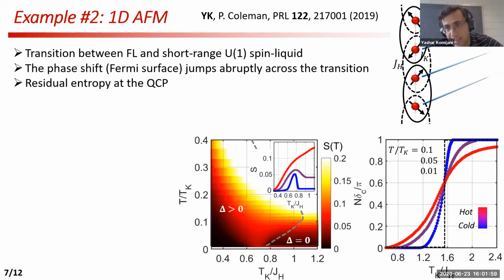Okay, so the second example is when I have antiferromagnetic coupling between the spins. In this case, when the magnetic coupling is dominant, I have a gapped spin liquid, a short range U1 spin liquid. It's very much like a Haldane phase of a spin 1 spin chain. So the transition will be between a local Fermi liquid and a spin liquid. Here you can see the phase shift as a function of the Doniach parameter, and it jumps 100% from pi to 0, and it becomes sharper at low temperatures. So again, loosely, we consider this as some sort of a jump in the Fermi surface, and this would be our Kondo breakdown transition. And this is the entropy, which shows the collapse of 2 energy scales from both sides. And there is a residual entropy at a low temperature, as you can see here.